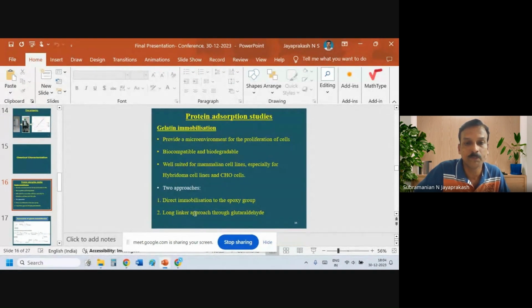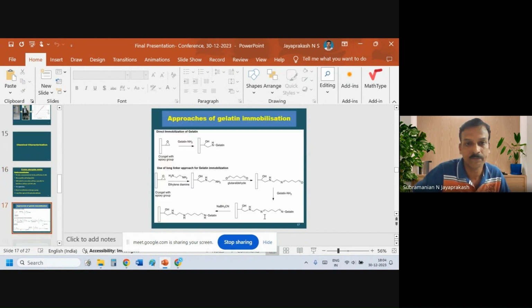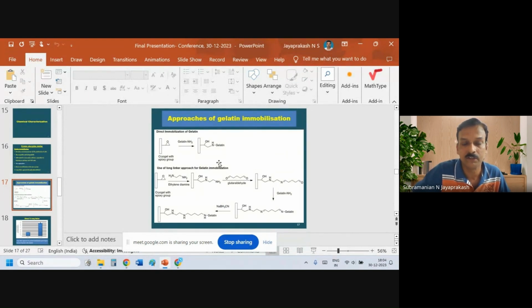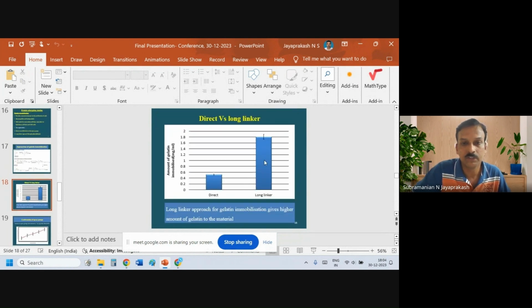So we did two approaches for immobilization. One is direct immobilization. Another one is the long linker approach through glutaraldehyde. So here you can see in this PPT, the direct immobilization of gelatin and also another method using a long linker approach. To conclude with this immobilization, we found that the long linker approach gave a higher amount of gelatin to the cryogel material. So we used the long linker approach for immobilization of gelatin to the cryogel material.